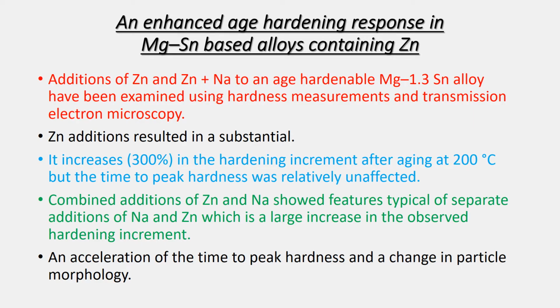An enhanced age hardening response in magnesium-tin based alloys containing zinc. Additions of zinc and zinc plus sodium to an age hardenable Mg-1.3Sn alloy have been examined using hardness measurements and transmission electron microscopy. Zinc addition resulted in a substantial increase, about 300%, in hardening increment after aging at 200 degrees Celsius, but the time to peak hardness was relatively unaffected. Combined additions of zinc and sodium show features typical of separate additions of sodium and zinc, which is a large increase in the observed hardening increment, an acceleration of the time to peak hardness, and a change in particle morphology.